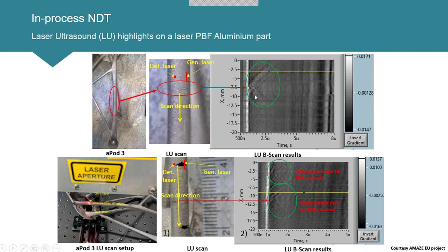This is to show, or basically starting to show, the capability of laser ultrasound, perhaps for in-process inspection, although we are doing it for a part. But the principle here is that this is as built, so we haven't machined it, we haven't polished, we haven't done anything to the part, so it's as rough as it is. Then we did another scan in an area which I marked here, which has no visible defects, but the X-ray CT, which I don't have time to show you, shows at least two defects around this area, and that's the reason I chose this area to scan.